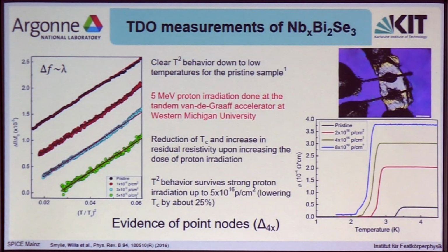So let's have a look at the measurements. While irradiating our TDO sample, we also irradiated a transport sample. You can clearly see by the increase in resistance and the reduction in Tc that we're doing quite some damage to our samples. However, if you look at the penetration depths, these do stay T-squared. So we think there's some clear evidence for the realization of the Delta 4x gap structure with point nodes in our samples.